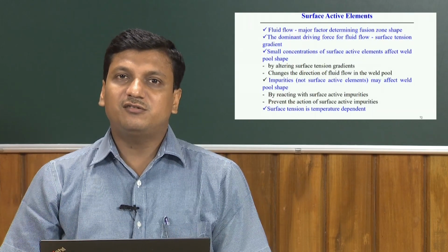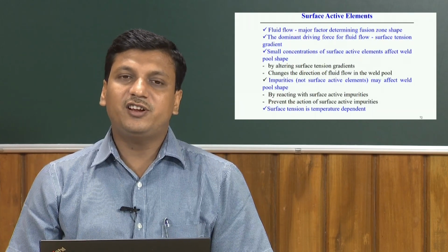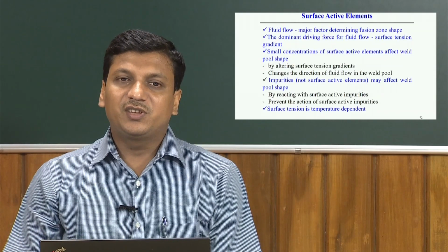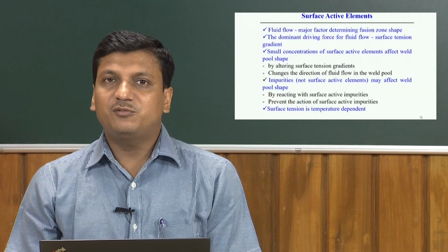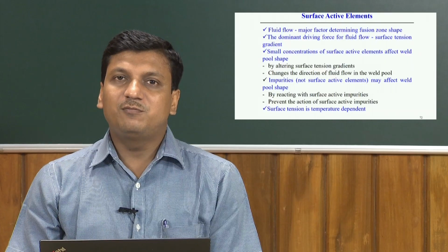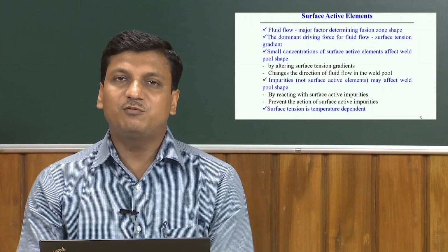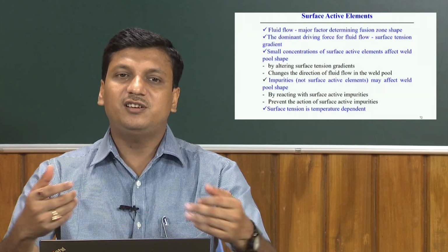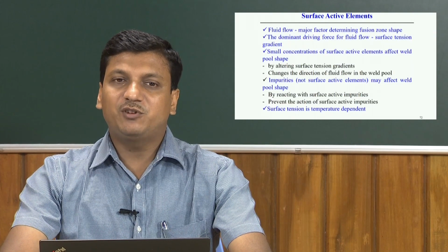When there is a change of the surface tension gradient, there may be changes in the direction of the fluid flow in the weld pool. And when there is a change of the direction of the fluid flow in the weld pool, that actually influences the shape of the weld pool.